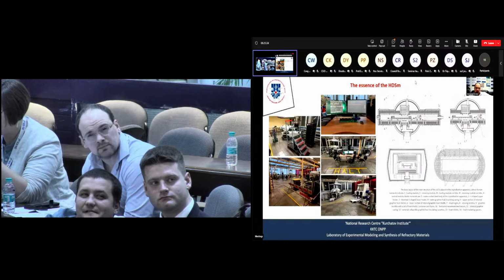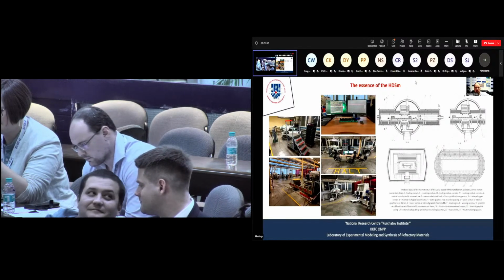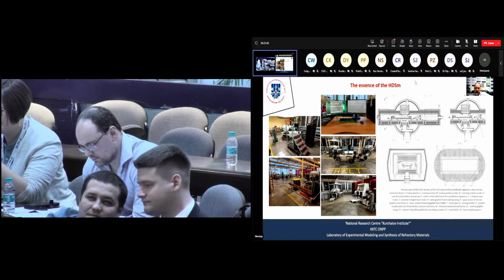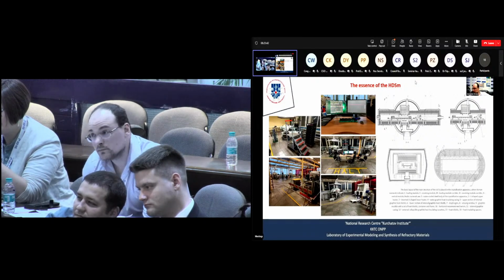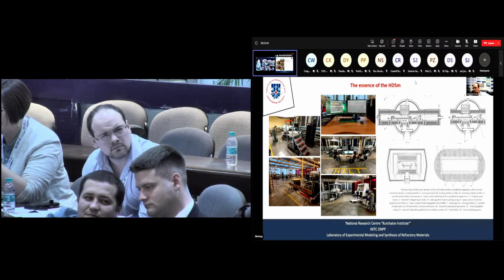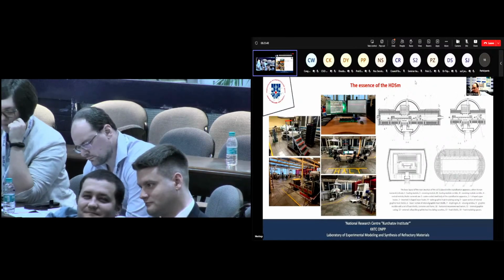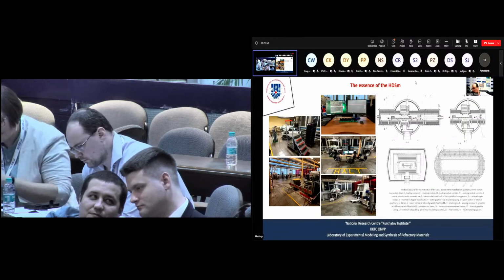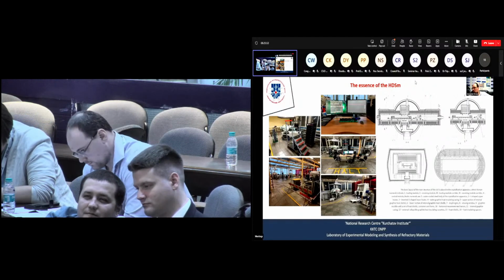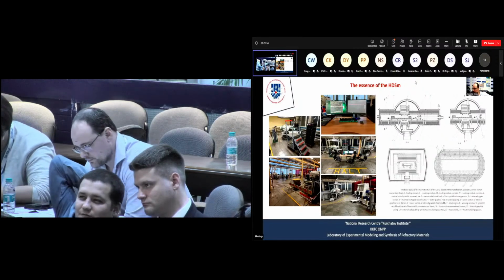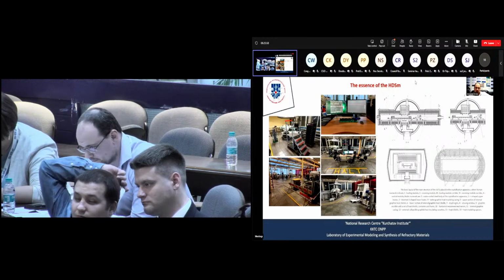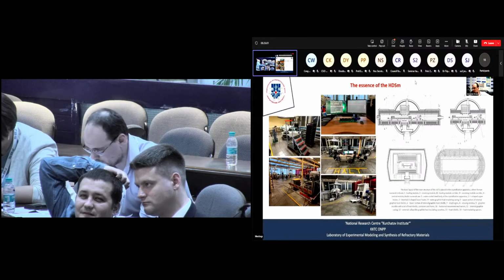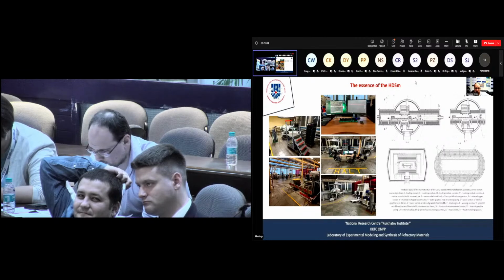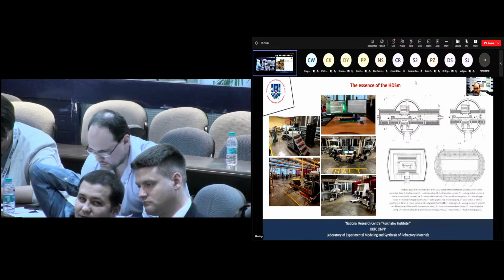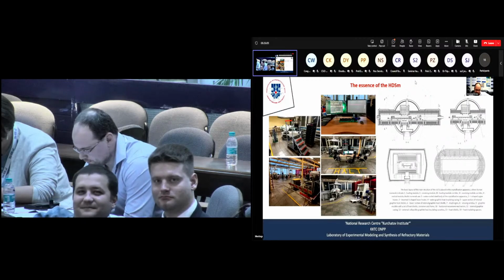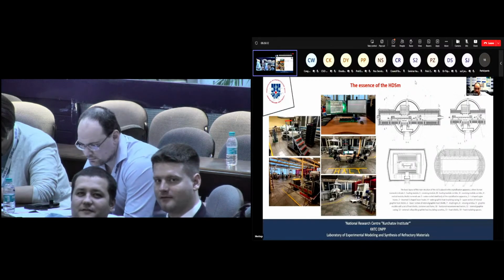A crystallized substance in the form of powder, crystalline solid, or ceramics is placed in a boat-shaped container, as depicted there. It is melted by moving the container through the heating zone, and after that crystallizes in the cooling zone. To obtain a strictly oriented single crystal, its seed is placed in the top of the container and visually observed, both for the moment of seeding and for the shape of the crystallization front.